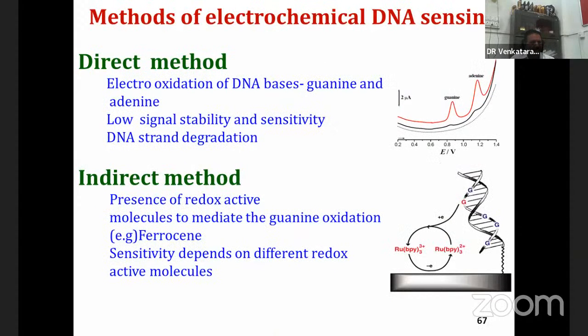And sometimes what we do is, if you apply a different range of potential, the bases present in DNA, like guanine and adenine, will undergo oxidation. For example, guanine undergoes oxidation at 0.8 volt, whereas adenine will undergo at 1.1 volt. And recently, by using graphene or other carbon material, you can see all the 4 bases give different oxidation peaks. That means when you put a single stranded, this is the signal. When you have a double stranded, you have an increase in the current signal that is directly proportional to the amount of bases present in your strand.